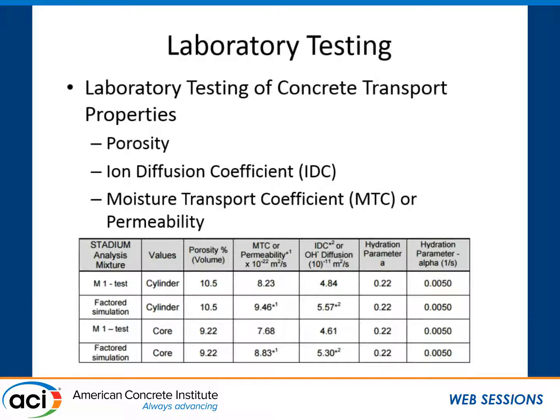The laboratory testing on service life engineering is a little different. What you'd have is the laboratory on transport properties, how things come into concrete and how they come out. So the porosity, the ion diffusion coefficient, and the moisture diffusion coefficient. Essentially, porosity tells you the number of available voids. The ion diffusion, how tortuous are those void systems? And then the moisture is, how does water move in and out? So what you would have is a mix, and in the case of the Navy, they wanted a mock-up put together as well as laboratory mixes. So you would have cylinders and cores, and you would have the test results from those so that we can use those going forward into a quality control program.